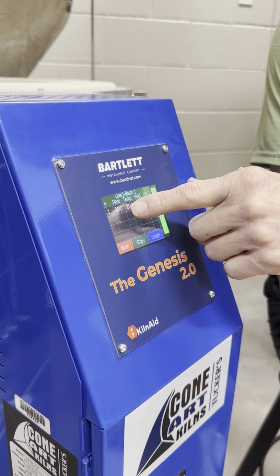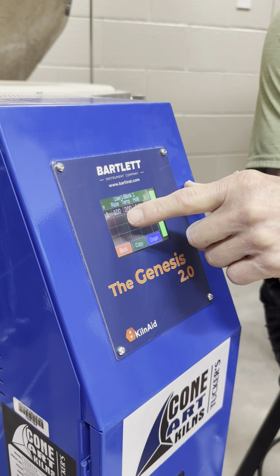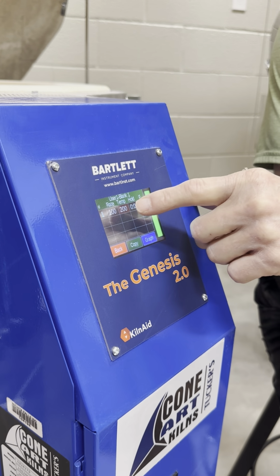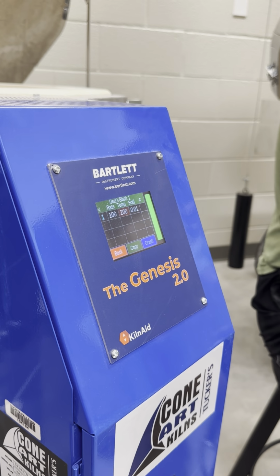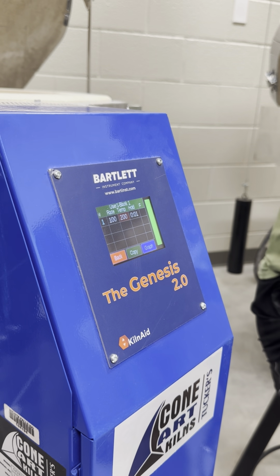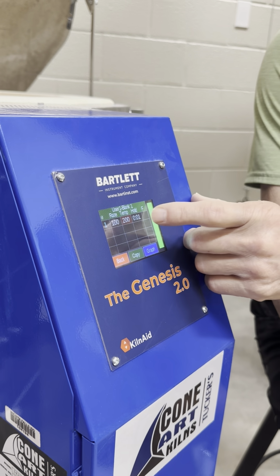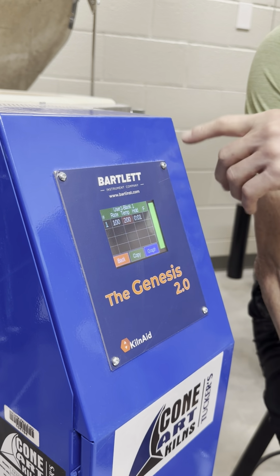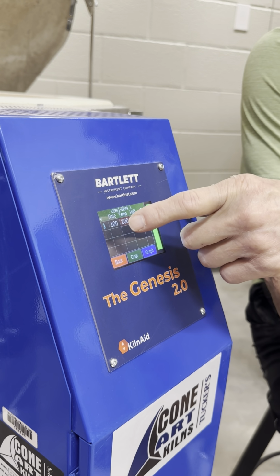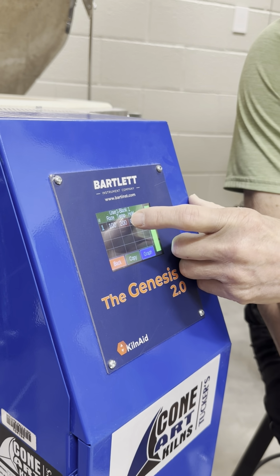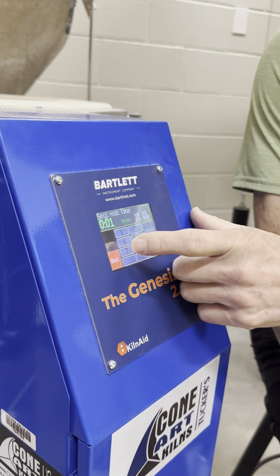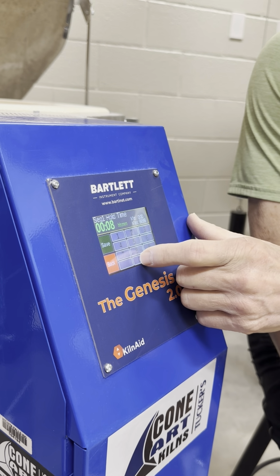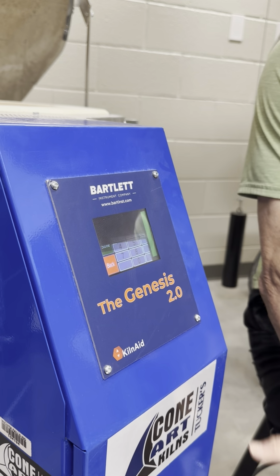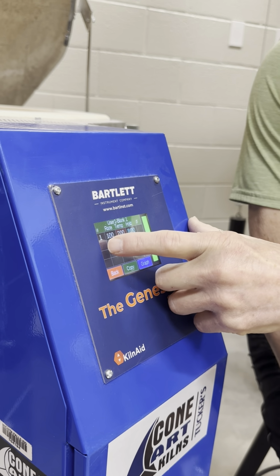Right now it's going to go up at a rate of 100 degrees an hour, up to a temperature of 200 degrees. So that's completely safe, right? And with big pieces I probably wouldn't go up any faster than 100 degrees an hour. I'm going to go over here and put on hold. I'm going to put 8 hours. Save. And then I'm going to add a segment.